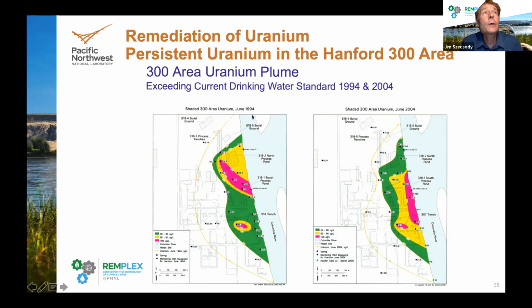All I'm showing in this diagram is, in 1994, after the initial cleanup, you see a uranium concentration, and 10 years later, you see a little bit different, but uranium is present in nearly the same location, so it's really persistent. The uranium concentration is low, so the main remediation technology being used is monitored natural attenuation. It does exceed drinking water concentration, but it's not used for drinking water. Phosphate is used in targeted areas to decrease uranium leaching.